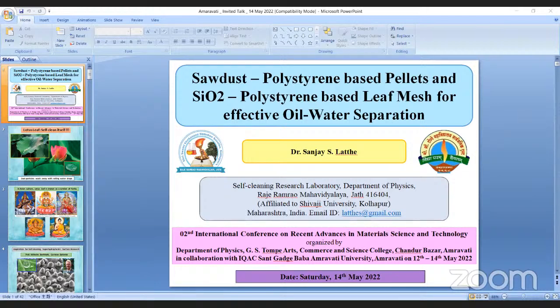As I said, 10 milligram per milliliter of polystyrene solution was prepared, and the coating solution containing different concentrations of silica nanoparticles, from 10, 20, 30, and 40 milligram per milliliter of hydrophobic silica nanoparticles in the polystyrene solution, was prepared and coated on the leaf mesh by dip coating.